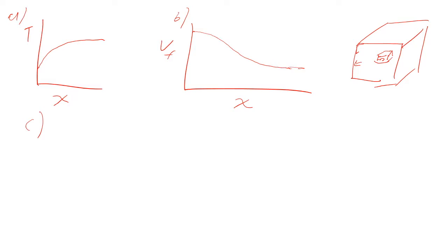At this point, is the surface under tensile stress or compressive stress? It's under tensile stress, but it's not moving anymore. Now the inside cools, and it contracts, and it's pulling against the surface. This gets into part C, I think.